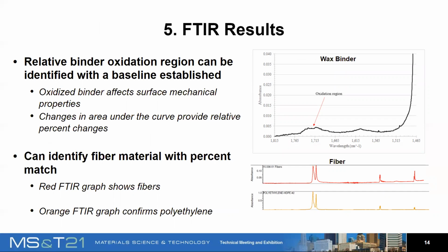Now here we could see a graph of a resulting spectra of our paraffin wax. Oxidation within the sample is important to identify, as oxidized binders affect the mechanical properties of the surface. In this graph above, the oxidation region is shown as a small peak at that 1700 point, and it shows us that the sample is oxidizing.